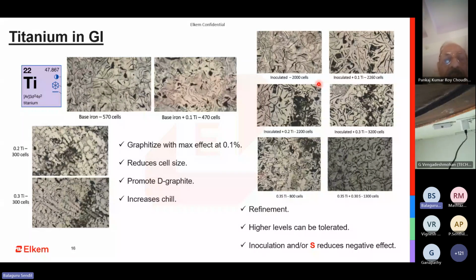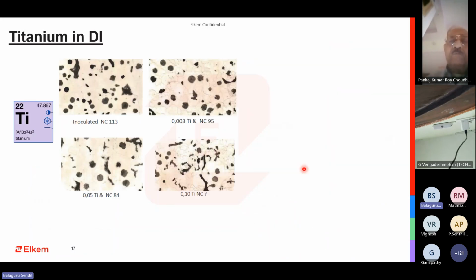So that's how we can solve this problem. When you are saying that you are having issues of titanium, we have to be very clear. It is not always a bad thing. It does refinement to your matrix. Higher levels of titanium can be tolerated in gray iron as compared to ductile iron. It is possible, and the inoculation and sulfur can reduce the impact of it. In ductile iron though, titanium will definitely reduce your nodule count. It promotes, or facilitates, the reversal of a nodule to a flake.